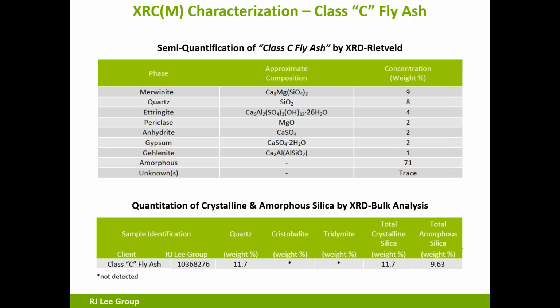With all of the products that we run that have undergone high temperatures, whether it's slag or fly ash or whatever it may be, we find that highly temperature treated products will come back as having mineral species that we can define. For example, quartz, 8%, 71% amorphous. Okay. So this is a good list that we use for safety data sheets to be able to identify what the ingredients are. And in that 71% amorphous is the amalgamated blended species that are hard, that are not going to break down, they're not going to salt, they're not going to dissolve. They are minerals, etc., that are bound together in an amalgamation.